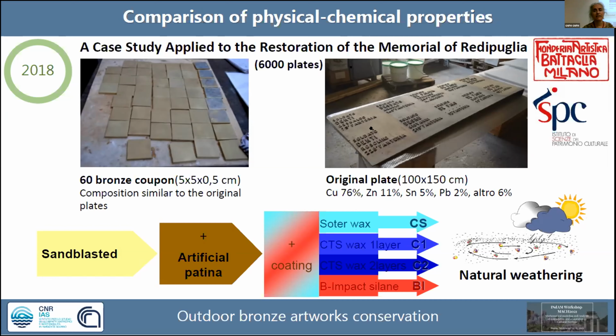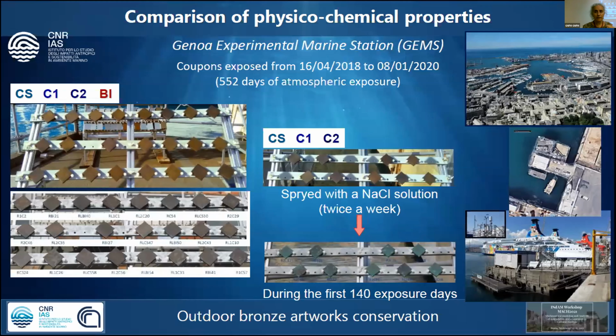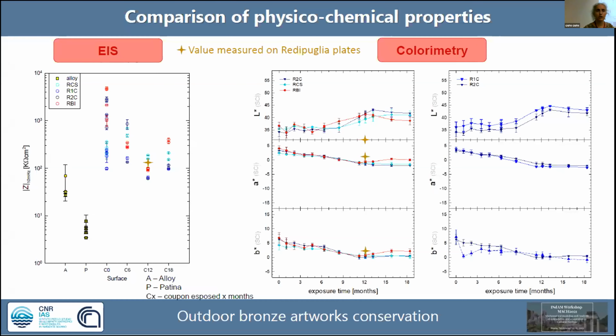In this case, for conservation reasons, the treatment was sandblasting, applying an artificial patina and then applying coatings. So we worked on coupons with the same alloy, and we made the same sandblasting, the same artificial patina, and then we tested different coatings and exposed the coupons to natural weathering, and then we went and made some measurements also on this place. The exposure was done in the station in Genoa in order to have all the parameters and to make the exposure in a standard situation. And we compared the data trying to focus on similarities and differences, and there are differences.